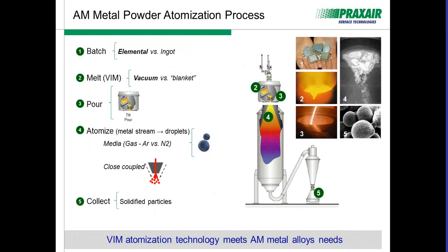When we atomize then, we want to look at the metal stream droplets. When we talk about this, we want to look at gas. What gas are we going to select? When we look at the gas that we're selecting, it can be argon or nitrogen. In some cases, it can be air or water. And so when we look at that, when you use argon, you can create highly spherical droplets that maintain a very spherical nature. When you choose something like nitrogen, you're going to pick up a lot of nitrogen along the way. And some people use water.